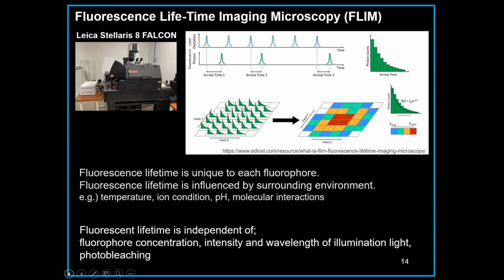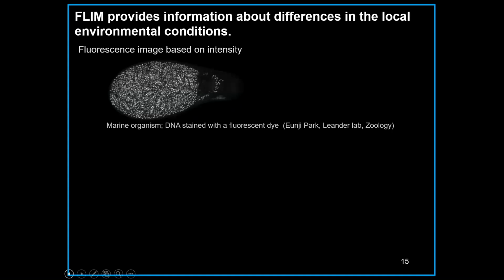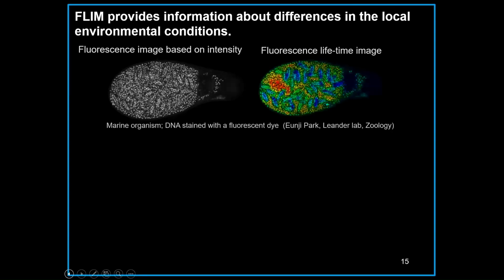And it has been used for many biological samples in our facility. This is an example of marine organisms. The DNA was stained with fluorescent dyes. So this is a fluorescence image based on intensity. It shows the localization of DNA-containing organelles. But if we do a fluorescence lifetime image, we can see differences in some compartments. Red shows short fluorescence lifetime, and blue shows longer fluorescence lifetime, kind of indicating that there are different compartments in the organism, and the environment is different.